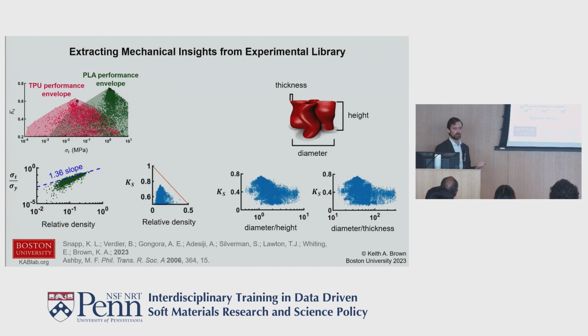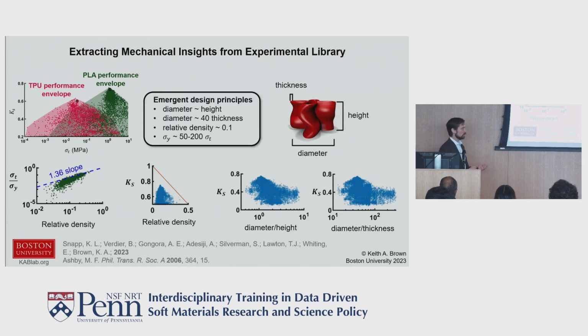And so this leads to interesting design philosophies: for components to be high performance, we want their diameter and their height to be commensurate. We want it to be roughly 40 times larger than its thickness. We want it to have a low relative density. And then for a given material, we want it at a working stress that's around 50 to 200 times less than its yield stress. So it really provides a lot of interesting design ideas here. When you have a data set that's 10,000+, it allows you to do this kind of large analysis very easily. And so, more to come on this.